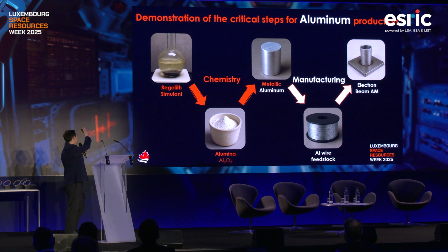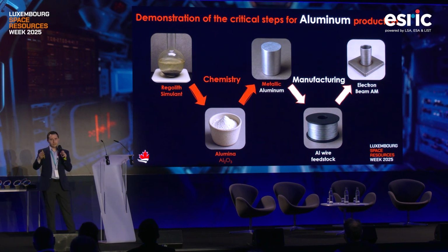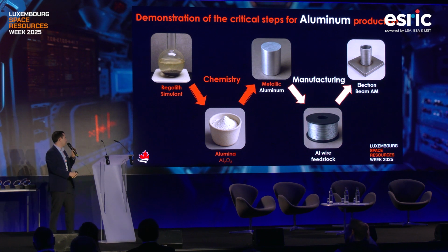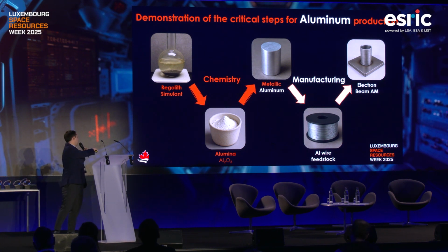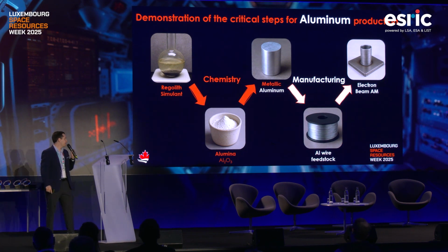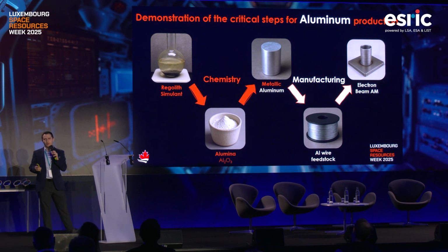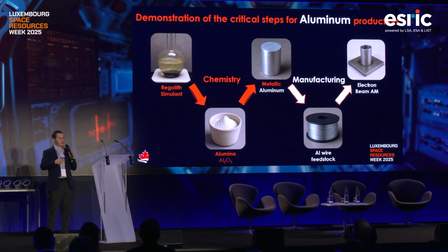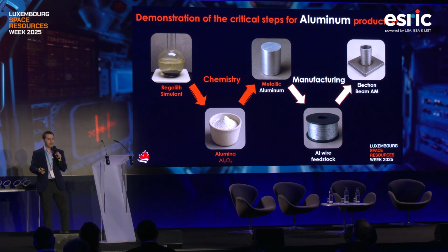So as you can see, we start with regolith, then we process it. We do some kind of pre-processing in order to obtain aluminum oxides, or alumina. And once we get that alumina, we electrolyze it to produce metallic aluminum. And then we go through manufacturing. So in this case, if you have a piece of aluminum, you can make a wire feedstock that could be used for additive manufacturing.